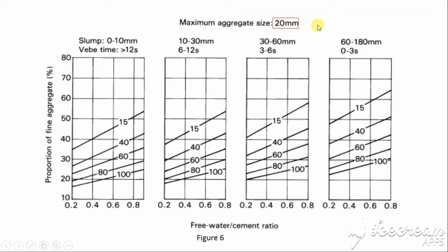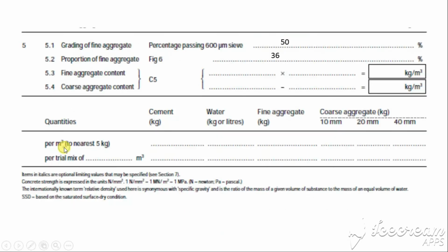Maximum size aggregate 20 mm, and then our slump 30 to 60, and then we will refer to this graph. This is the line for 50% percentage passing 600 micrometer. You need to create the new line here, and then our free water cement ratio 0.54, project to this line, and then we can get the proportion of fine aggregate is 36%. Use this value to calculate the fine aggregate content. Refer to the C5 formula.